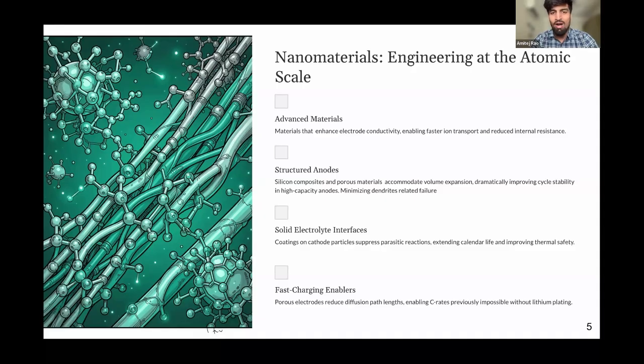Number one, using some advanced materials. In a battery, imagine that we have an electrode, right? In that electrode, there are certain electrochemical reactions which need to happen. Taking an example of a lithium-ion battery, on the anode, people particularly use graphite. The reaction happening is that lithium intercalates between the layers of graphite. It goes and sits between the layers of graphite. Now, the amount of lithium ion stored will determine the capacity of the battery, and the speed of this storage will determine the charging speed.